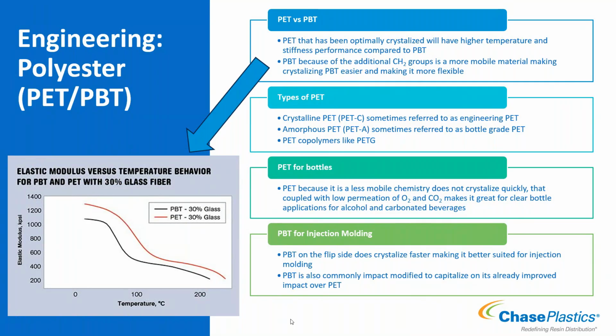Then you have amorphous PET grades, sometimes referred to as bottle grade PETs. These are ones where when we process it, we freeze it quickly so it doesn't allow it to crystallize. So you effectively make an amorphous version of it. That's what you get out of your bottle type PET grades.